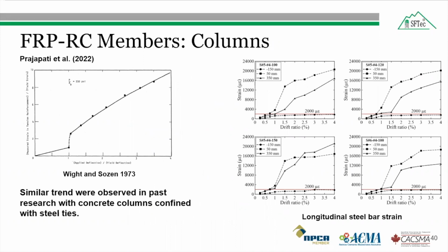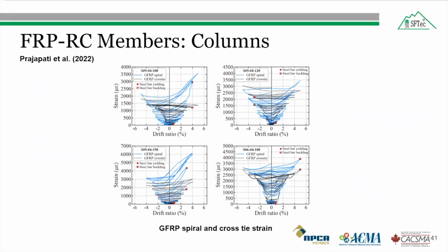So therefore, the behavior of the longitudinal steel bar was unaffected by the type of transverse reinforcement used, either steel or GFRP. So here you can replace the steel transverse reinforcement with the GFRP reinforcement, and the behavior will be almost the same, and the structure will be more corrosion resistant. The glass fiber reinforced polymer spiral and cross tie effectively confined the concrete column after the yielding of the longitudinal steel bar.